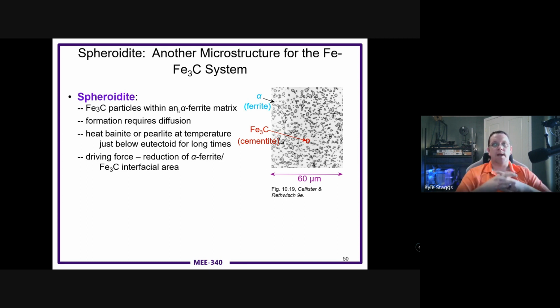So it's important to understand that aspect of the chemistry, because that driving force is what causes droplets to come together and merge. There's a ripening effect. There's a bunch of other particular terms that apply to that, but it's the same kind of idea: it wants to minimize the surface area interaction, and in this case, the small droplets have a lesser surface area than all of the long stretches of curvy, windy, plate-like structures that the cementite forms in pearlite.